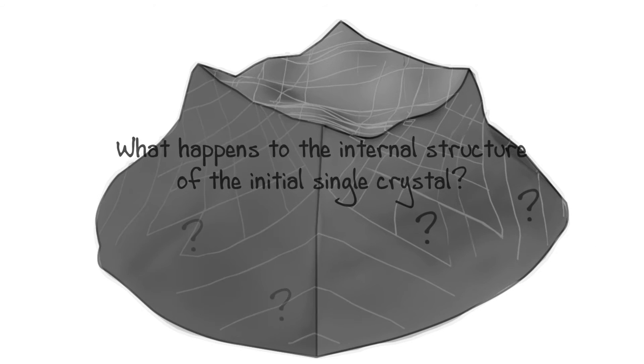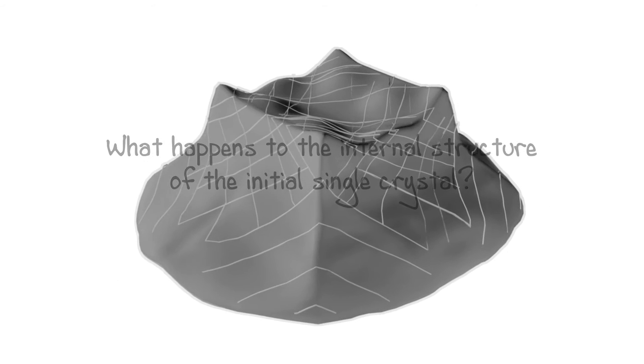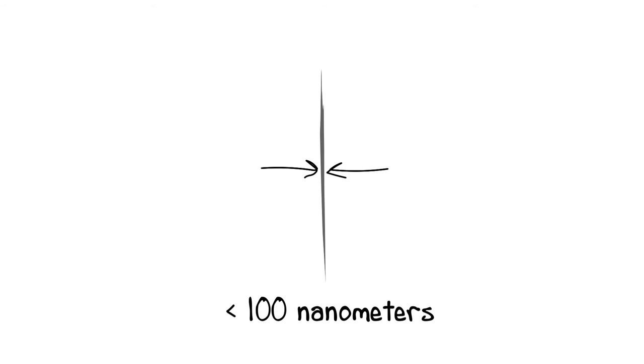With such severe deformation on the outside, you might be wondering what happened to the internal structure of the initial single crystal. To study this, we used a focused ion beam to prepare a thin lamella, less than 100 nm thick, from the middle section of the deformed cube.